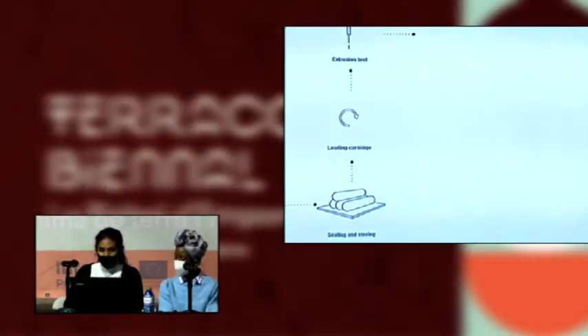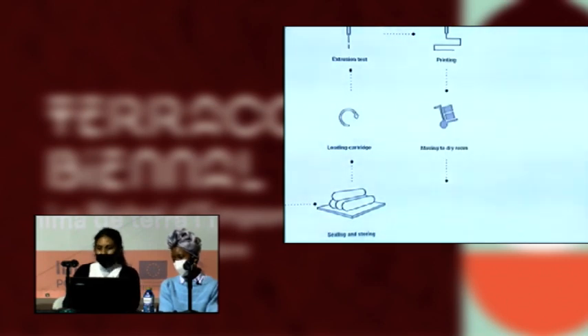And then they are sealed and stored well so that they aren't exposed to the air and dry out. And then we load the cartridge into the KUKA, and we do an extrusion test to check the required air pressure and the material consistency for printing. And then we start the printing. After the piece has been printed, we move it to a dry room to make sure all the water is evaporated and it's completely dried.